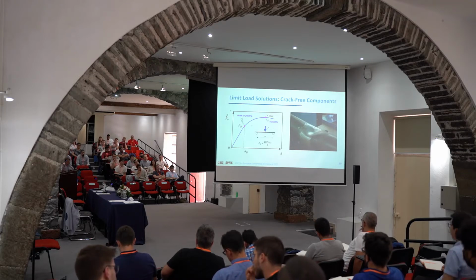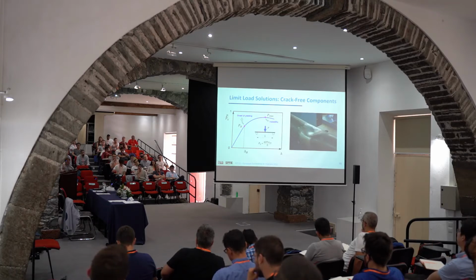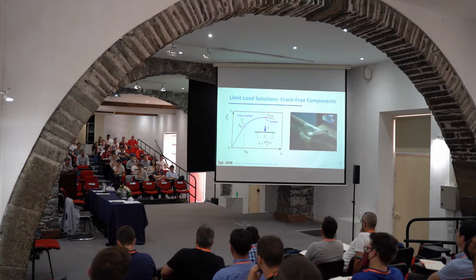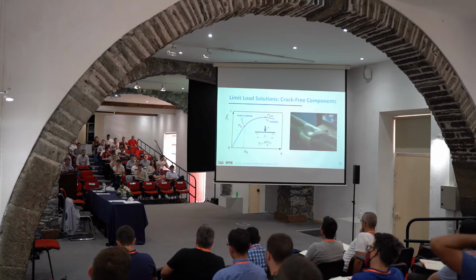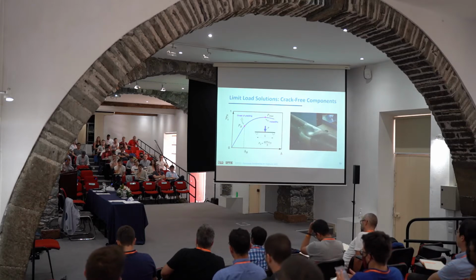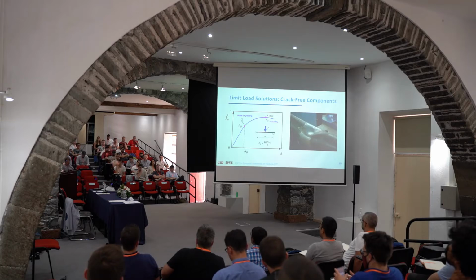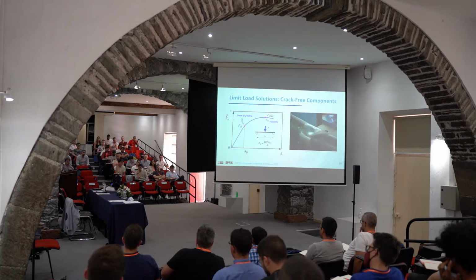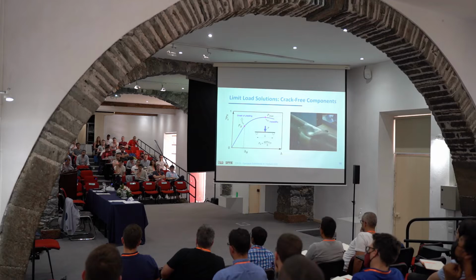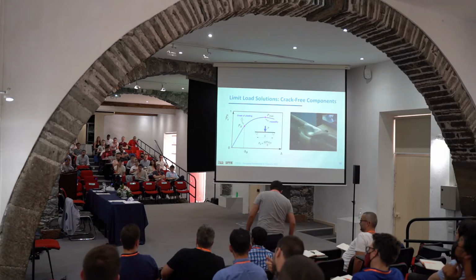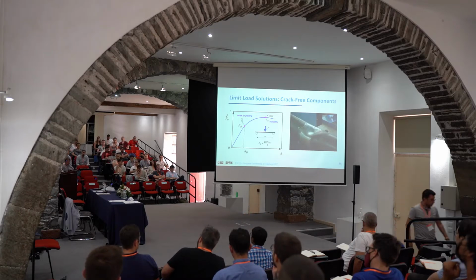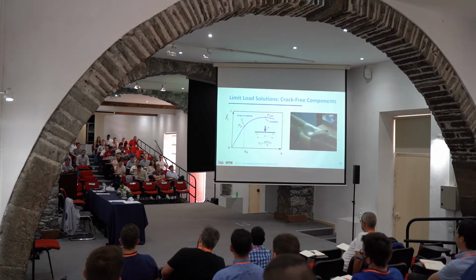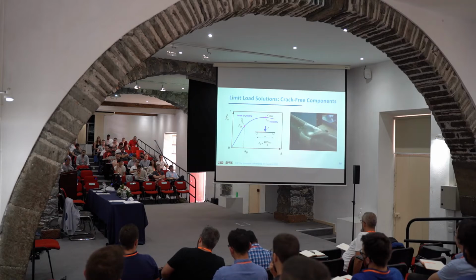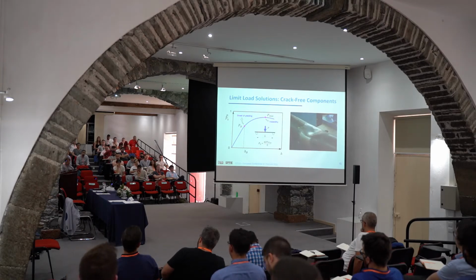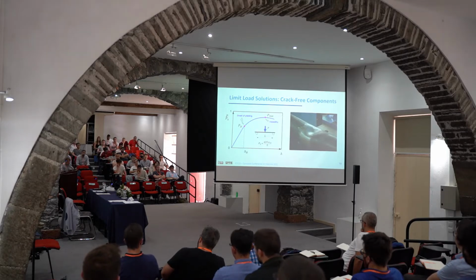At a certain point you will reach instability. This is not fracture. The specimen will not necessarily break. It's like buckling. If you remember Euler's beam, all that stuff about the critical load, it's like a geometrical imperfection. When you have the eccentricity, so when the applied bending moment is bigger than the restoring moment, buckling occurs. So it may eventually break, but the root cause of the failure is actually geometrical. It's not the material. The material is involved, of course, because it's plastic, but the instability does not necessarily cause fracture. But the structural component loses its capacity of supporting load.